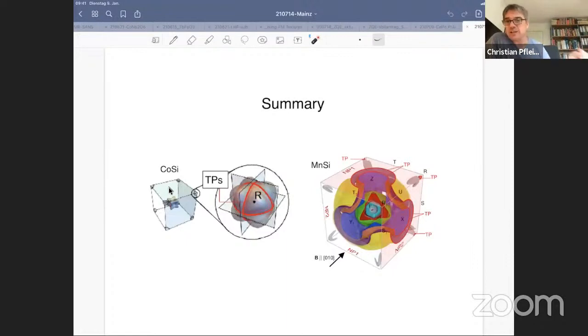Yeah. But you can ask, well, you do see Fermi arcs in the cobalt silicon experiments, what's going on there, right? And there's no problem with that, because this is basically a flow of Berry curvature, not between the nodal planes and some charges. It's just that, I guess, it wasn't realized that close to the 4-fold points, there's another 2-fold point, and that is connected with the nodal planes. And that's what was published recently, I guess, in the Nature Communications paper.